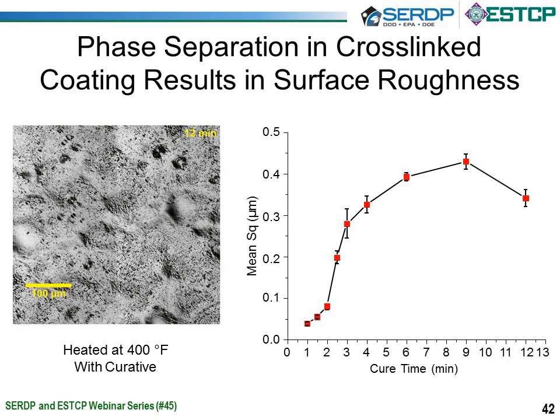At 12 minutes, you can see a slight decrease in the surface roughness. We believe that this reduction, albeit slight over the 9 minutes, is the polymer system being locked into place, yet continuing to react or cross-link with the resulting unreacted moieties that remain. And we believe that because this is above the glass transition temperature, segmental motion is resulting in this slight rearrangement and lowering of roughness.